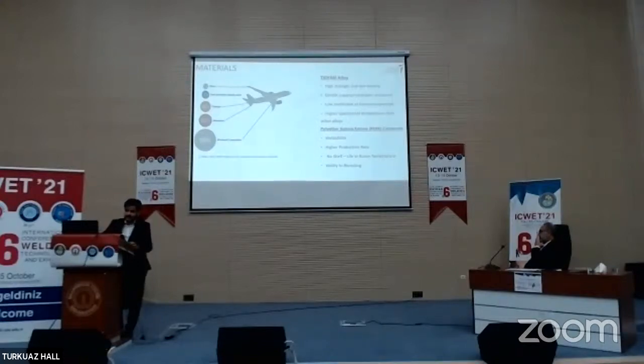Although thermoset composite materials are used, the demand for thermoplastic materials is increasing day by day. This is increasing because thermoplastic materials have several advantages. The first and foremost advantage is weldability. Since you can melt thermoplastic composites, you can easily give shape and easily mold this compound. It also increases your production rate and gives you the ability to recycle, and thermoplastic composites have no shelf life limit at room temperature.